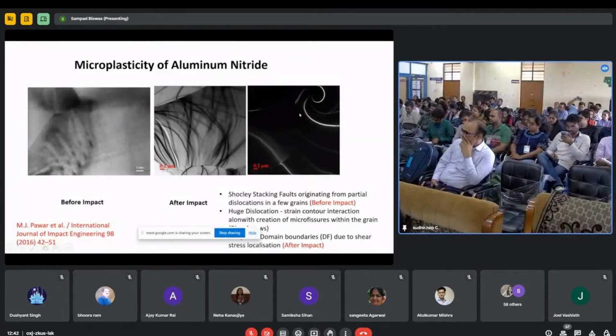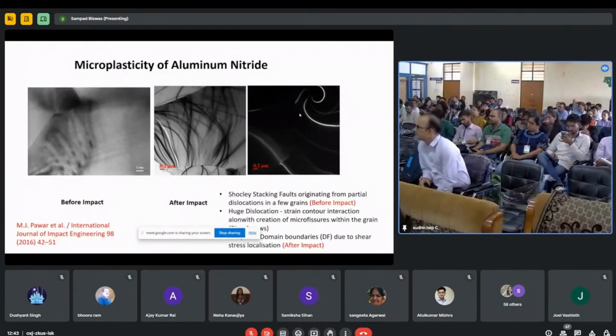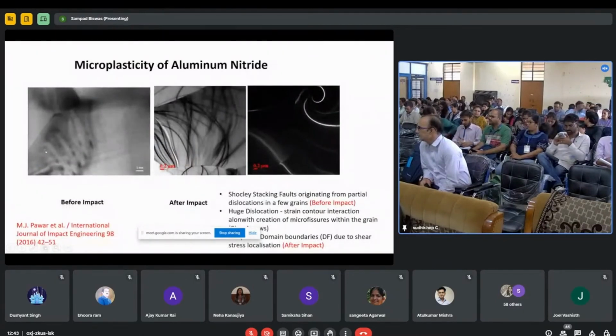We took a transmission electron microscope image of the failed sample. We carried out one typical experimental arrangement so that the debris after the impact could be collected, and this debris was analyzed further to understand the mechanism of failure. From that debris, we took this sample, the thin section. We have seen here the Shockley defect, and Shockley stacking faults originated from the dislocations. You can see this is present in the original material.